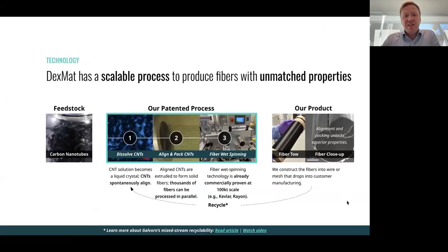DexMat has a highly scalable process for making Galvorn. The way this process works is we take raw carbon nanotubes, which come in a pelletized or powder format, and we dissolve them in a solvent. At very high concentrations, when we make a carbon nanotube solution, it forms a liquid crystalline phase, which basically means that the carbon nanotubes start to spontaneously orient and pack together with one another. And what you end up having is a polydomain liquid crystal.